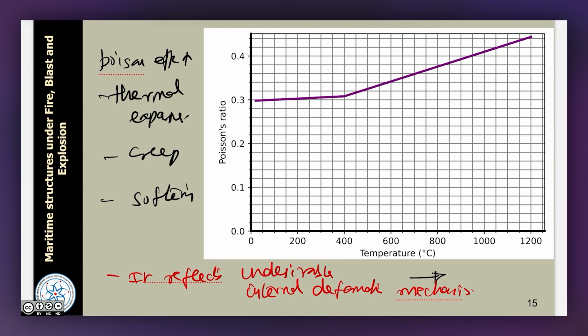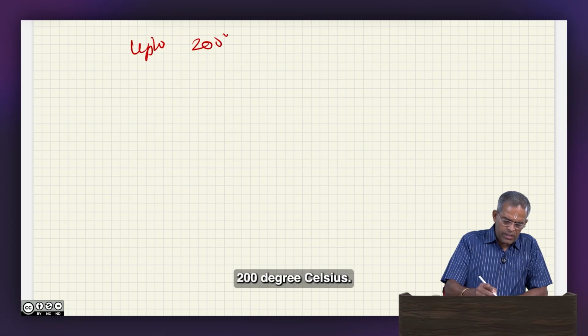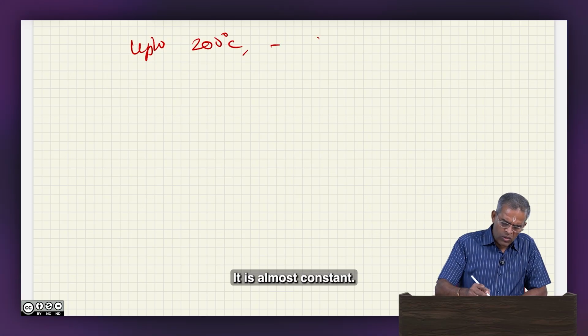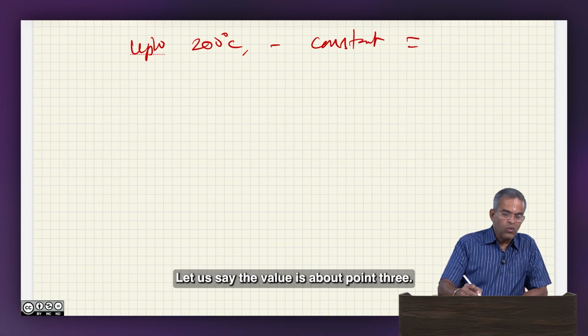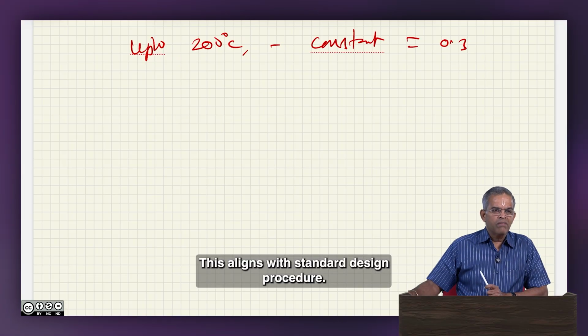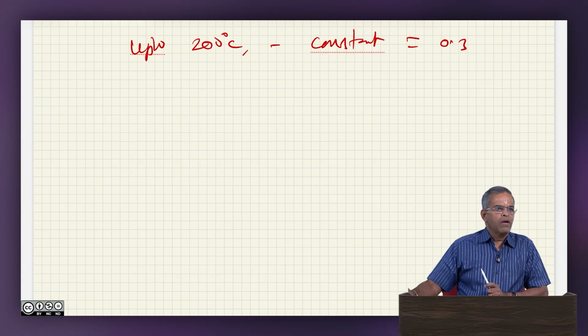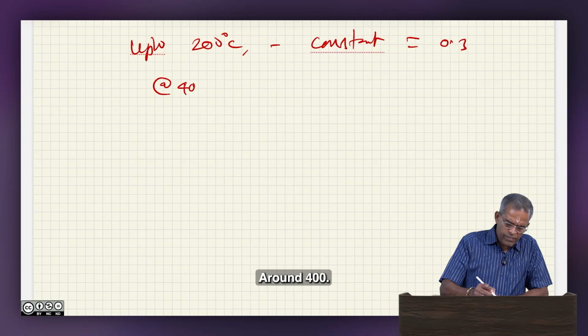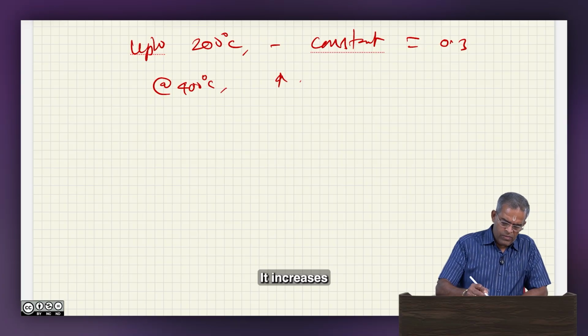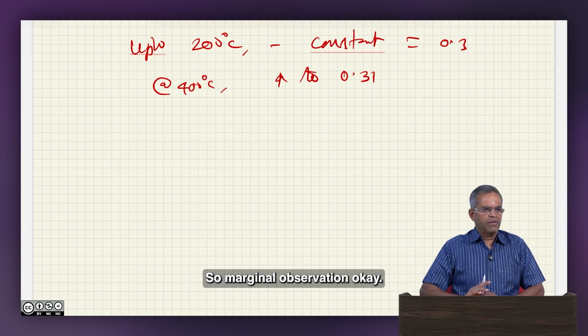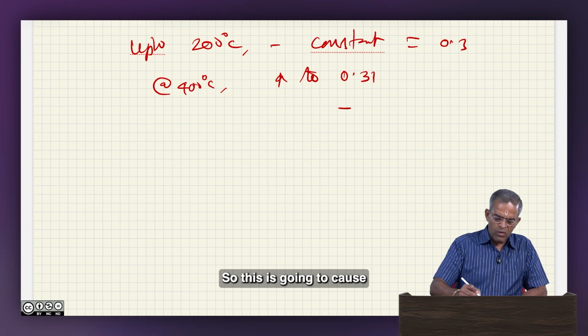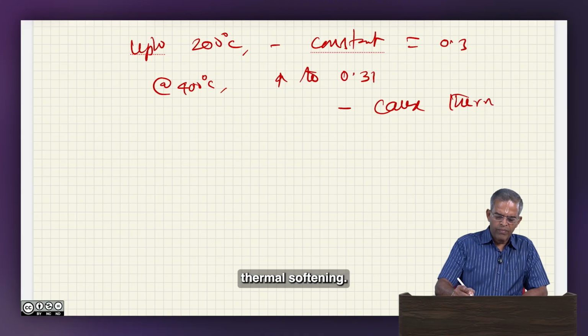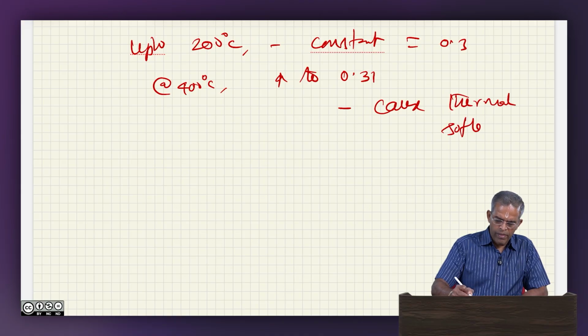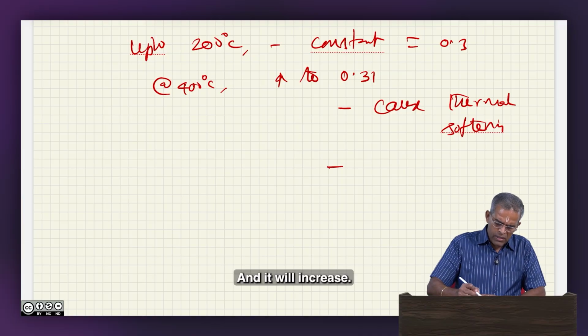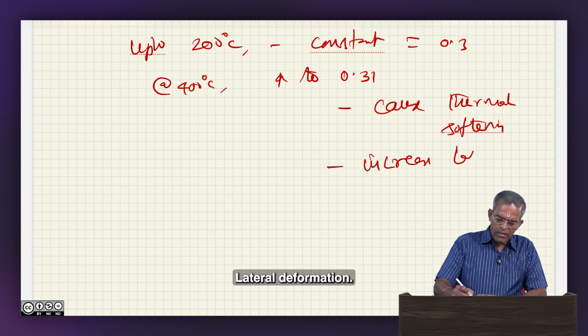Now, up to let us say 200 degrees Celsius, it is almost constant. Let us say the value is about 0.3. This aligns with standard design procedure. Around 400, it increases to 0.31, the marginal observation. Okay. So, this is going to cause thermal softening, and it will increase lateral deformation.